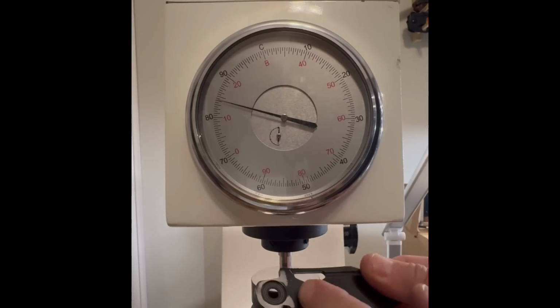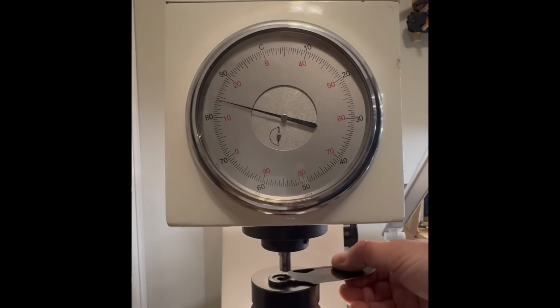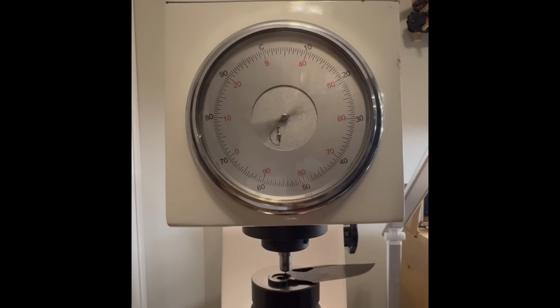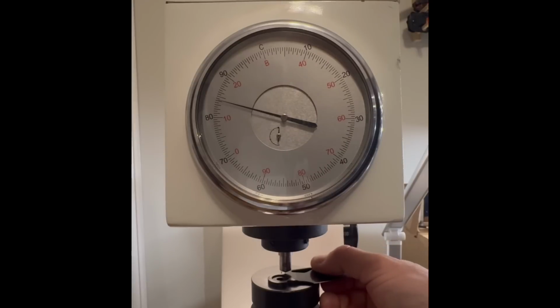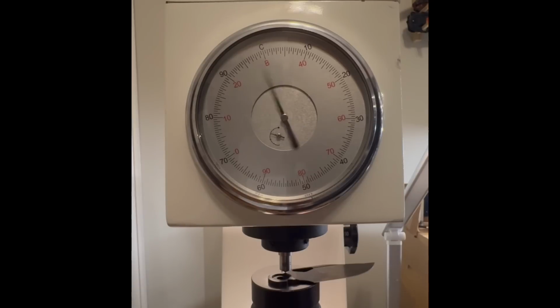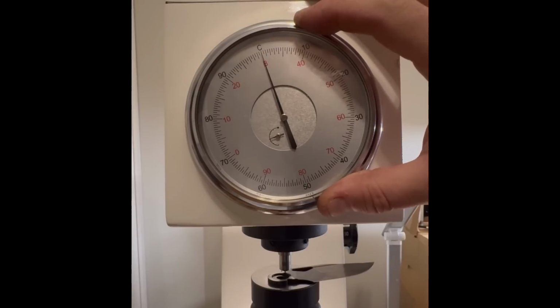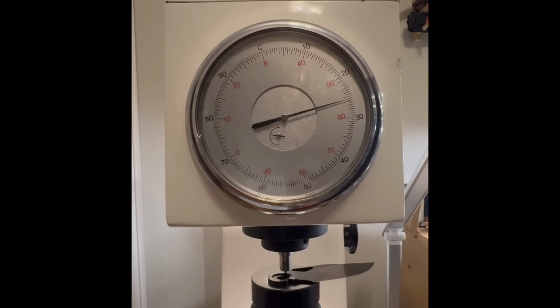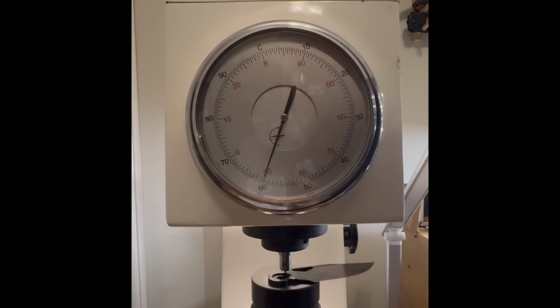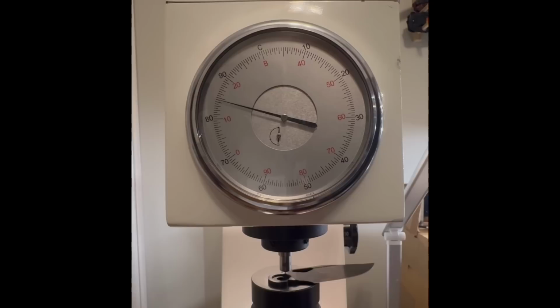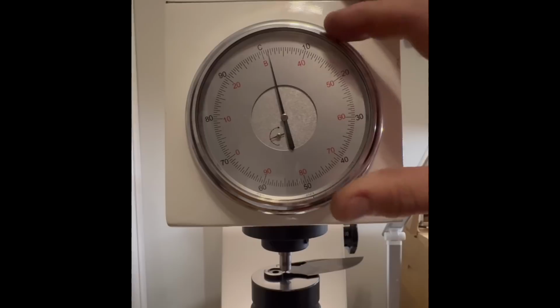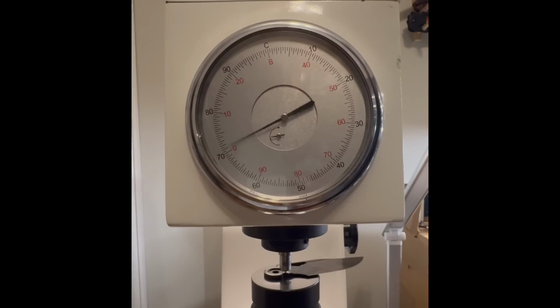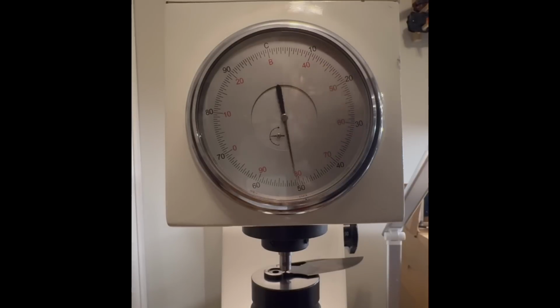And next I am going to move it to the uncoated area and try it again. So I've heard YouTubers say that DLC coating can lower the measurement by 1 point HRC. We'll find out. I was certain that it's not true, and that's the first time I'm doing this particular blade on the Rockwell benchtop. Ooh, we got over 60. 60.4 HRC. Interesting. Unexpected. This is indeed 1.1 point higher than the lowest measurement I did on the DLC coated area. Interesting. Let's see how it performs in the next few.